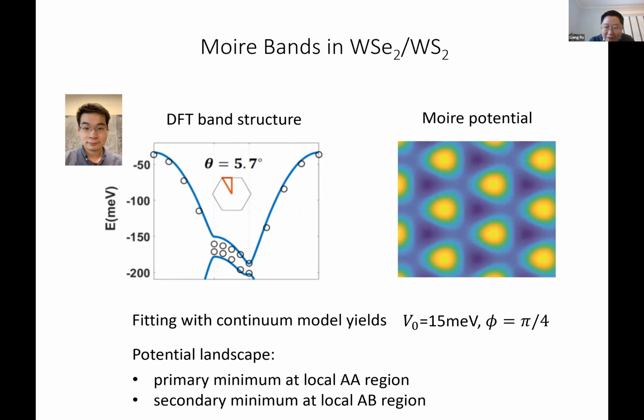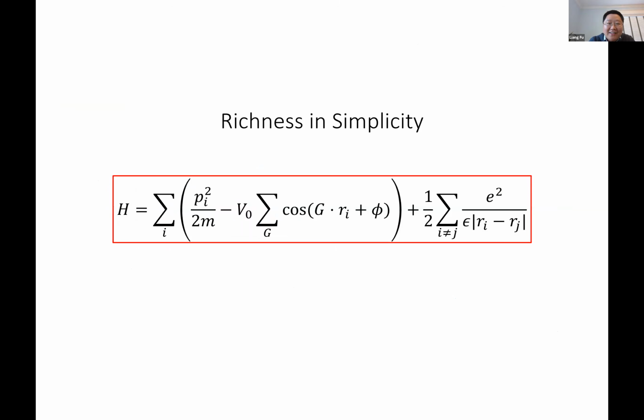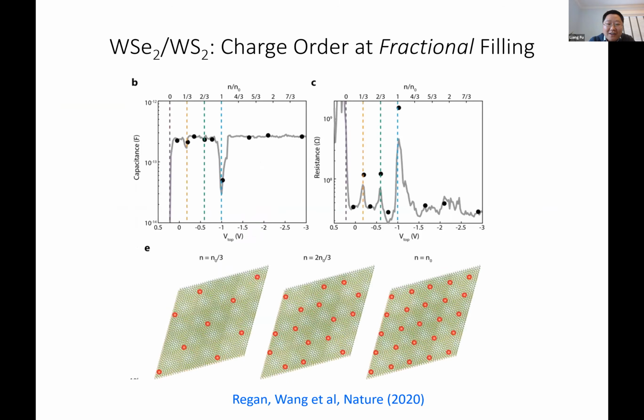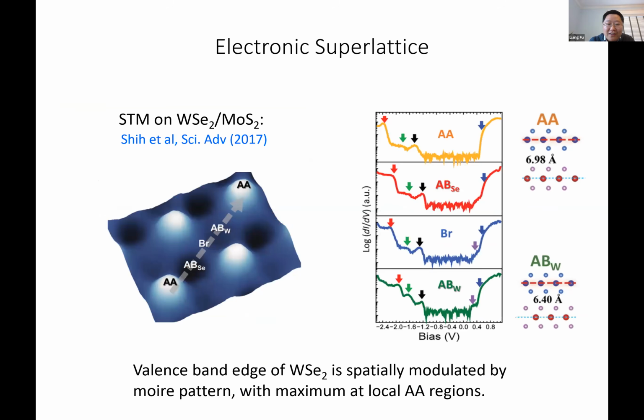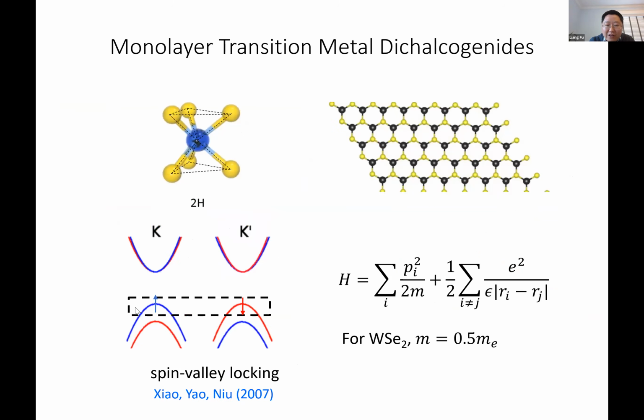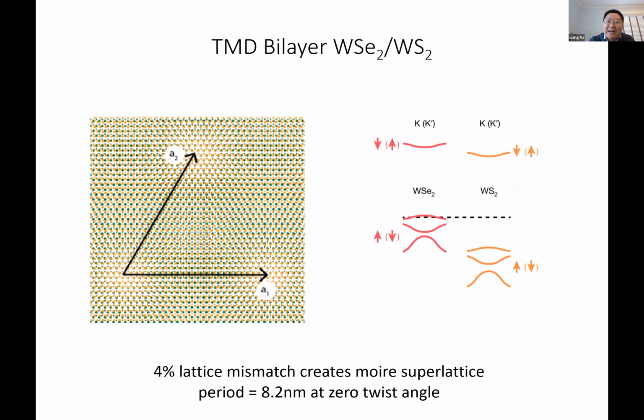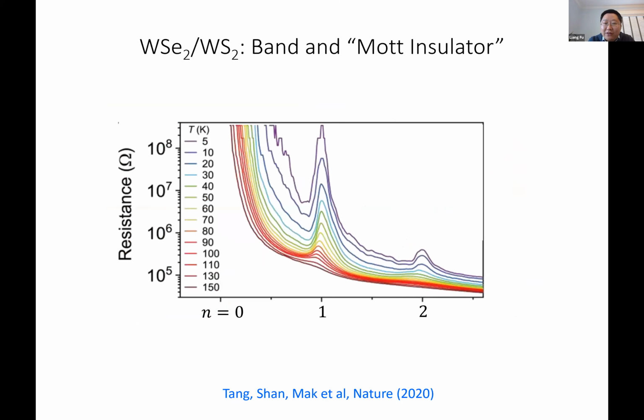Yeah, they are very different, for the following reason. In the TMDs, the underlying material in monolayer form has only parabolic bands. So what we are dealing with is just parabolic bands in the presence of a Moiré potential. And when the potential is deep, then you naturally expect states to be localized near the potential minimum. And this is exactly what happens at large Moiré period.